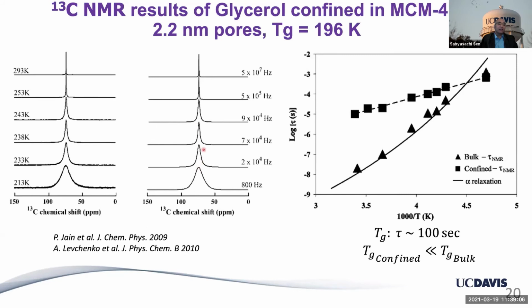And this rotation also, you can figure out that this rotation is isotropic. So it's not about any specific axis in the molecule, but it's rotating around all possible axis orientations. So the axis gets randomized with time. So this isotropic reorientation is what it is called. So when you plot this isotropic reorientation time scale, log of that, as a function of inverse temperature, then we get these triangles for the bulk glycerol. And what I'm showing you with this solid line is the shear relaxation time derived from the viscosity of supercooled glycerol. And you can see that over 5 orders of magnitude in time scale, the viscosity or viscous flow of glycerol is controlled by this isotropic reorientation of the constituent molecules.